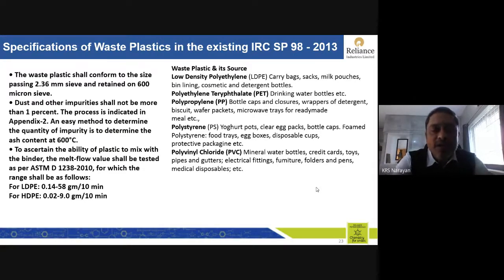So what happened was the contractors were given this code to use these types of waste plastics. They started sourcing these plastics, and many of the times they came out with a problem stating that some of the rigid plastics were not melting at 160 degrees Celsius. It was taking around 250, 260 degrees Celsius to melt PET. And of course, PET has a better value in terms of recycling, as well as different other great benefits of use in manufacturing textile yarns. But because of this code, they were forced to use such material.